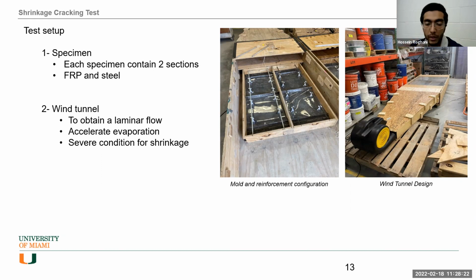And the reinforcement, here we have to understand that if we don't see the cracks, we cannot compare them together, so we are trying to make the conditions severe, because this temperature and shrinkage reinforcement does its job after the concrete cracks. Before the cracks, they are not doing anything. So when the cracks show up, they start keeping the cracks together. And when they can keep them tight enough, you will not have the penetration of chlorides or other chemicals inside your concrete, which is our goal.